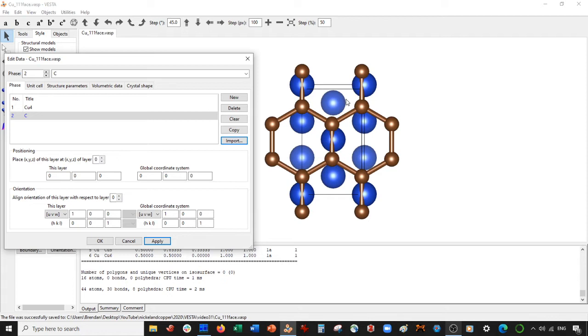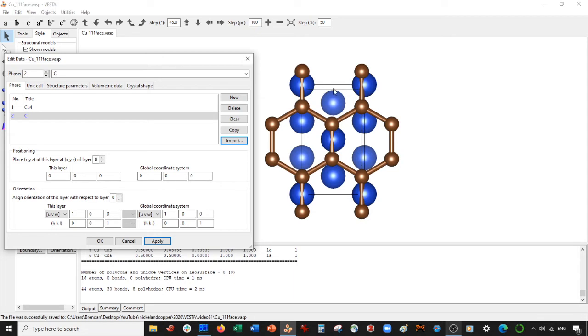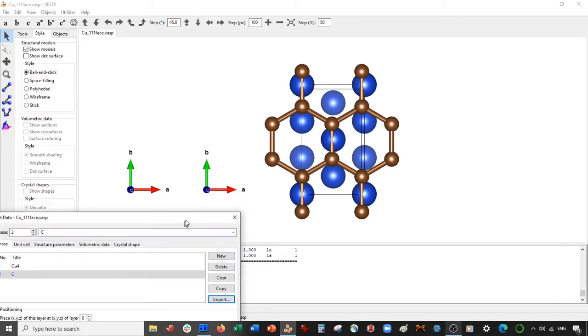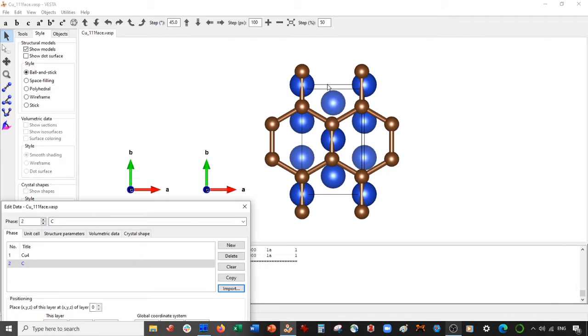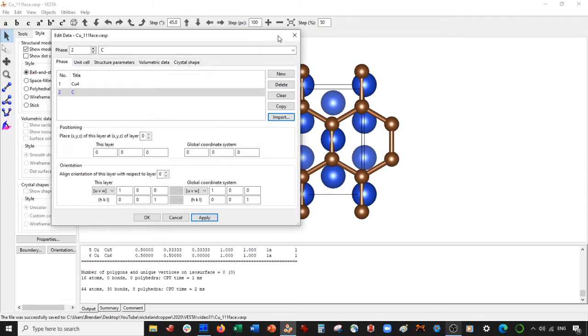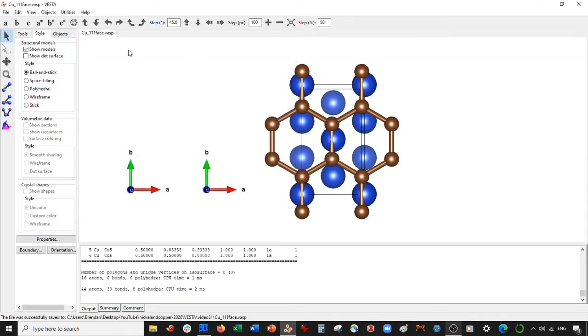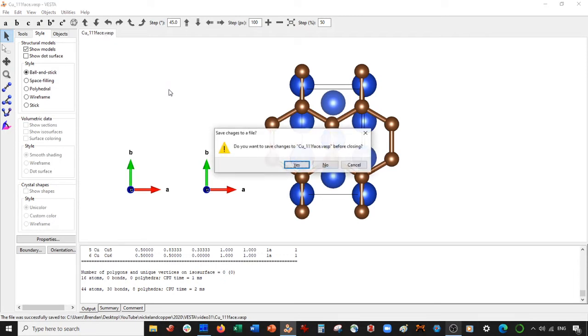So what I do is, and this only really is viable if it's a really small lattice mismatch, which this is like less than 5%, I think on each side, just about less than 5% here. I'm going to make the lattice dimensions for the graphene. So this will be in the B dimension for the graphene, I'm going to make it same as the copper. And in the A dimension, I'm going to make it same as copper as well. So exit out of here and I'm going to exit out of here. I do that with control W.